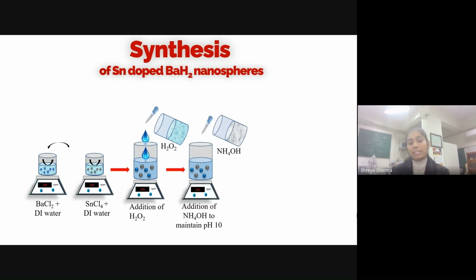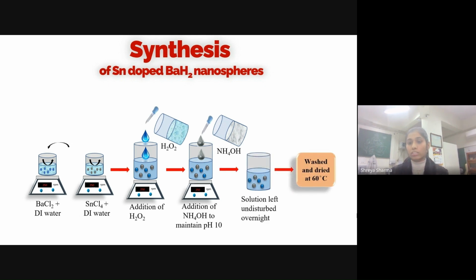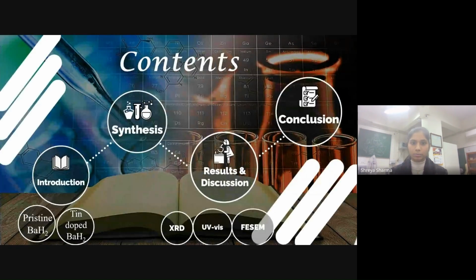And the pH was maintained at 10 by ammonia water. After which the final solution was left undisturbed overnight, and finally it was washed and dried at 60 degrees Celsius to obtain the final tin-doped barium hydride material.